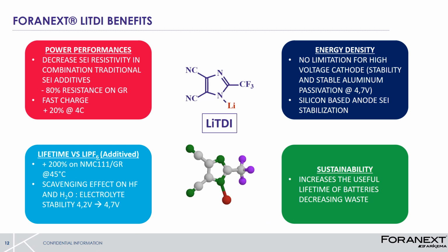To conclude, I would like to remind you of all the LiTDI benefits. In terms of power performances, it decreases the SEI resistivity in combination with a traditional SEI additive, and improves fast charge performances, especially at 4C. For the energy density, with the LiTDI, we have no limitation for high voltage cathodes because of the stability and the stabilized passivation layer formed with the LiTDI, we can go to 4.7 volts.